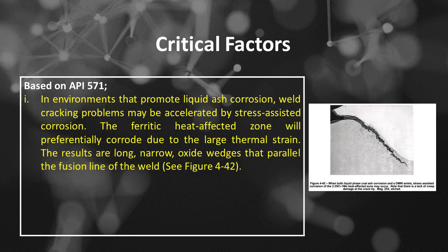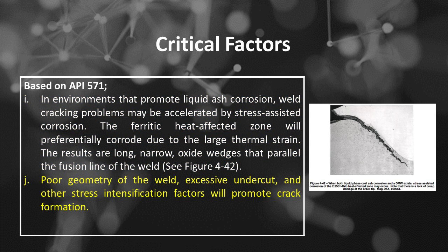The ninth is in environments that promote liquid ash corrosion, weld cracking problems may be accelerated by stress-assisted corrosion. The ferritic heat-affected zone will preferentially corrode due to the large thermal strain. The results are long, narrow oxide wedges that parallel the fusion line of the weld, see Figure 4.42. When both liquid phase coal ash corrosion and a DMW exist, stress-assisted corrosion of the 2.25 Cr 1 Mo heat-affected zone may occur. Note that there is a lack of creep damage at the crack tip. Mag. 25X, etched.